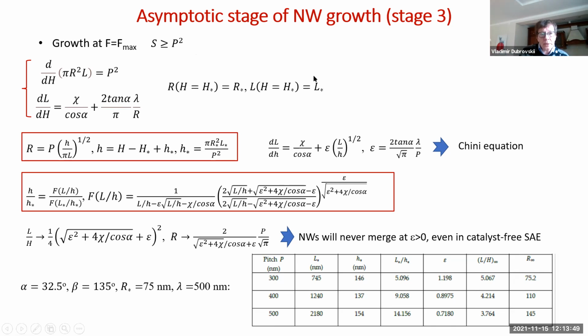And then I have the boundary conditions. But what is interesting is that the radius now depends on L. And therefore, for dL over dH, I now have an equation which is actually not as simple as we thought before. It's called a Chini equation, where dL over dH contains the contribution from the top plus epsilon times the square root of L over H, where epsilon is proportional to the lambda and inversely proportional to the pitch.